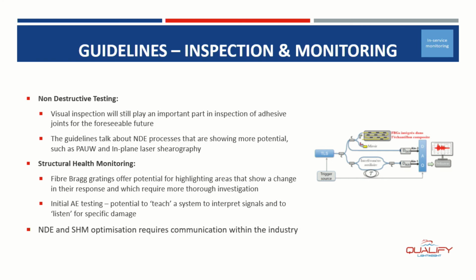So we need to test or model with that level of defect in place and make sure that not only the performance is sufficient at that stage, but also that that defect can't grow before the next inspection point. If we get a defect that grows quickly, we can obviously get critical failure, and we must prove by testing and modelling that that's not going to be the case. At the moment, we're limited in the processes, especially for things like adhesive joints, because things like kissing disbonds give us all a headache, obviously.